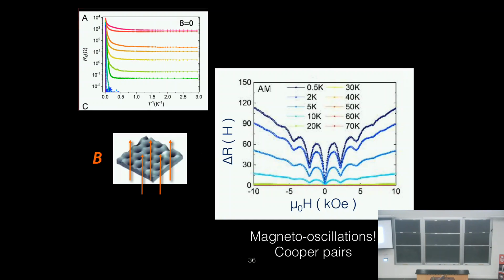So now here are those metallic behaviors, and what we're plotting here is the resistance, the magnetoresistance, as a function of field for one of these at different temperatures. And what you can see again are oscillations. So there are Cooper pairs that are involved in this metallic state. It's as direct evidence as we can imagine. So like the Bose insulator, we see Cooper pairs by looking at these quantum oscillations.